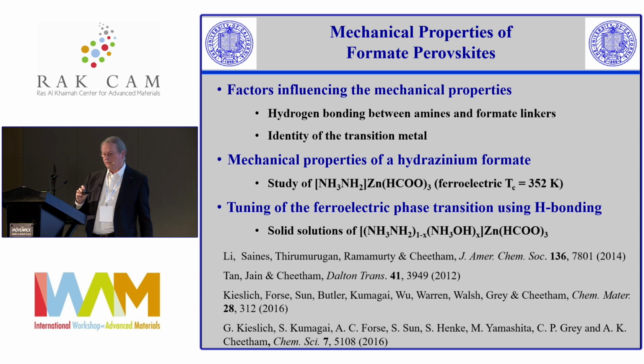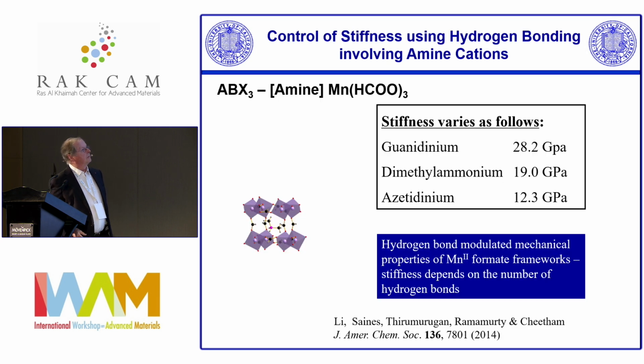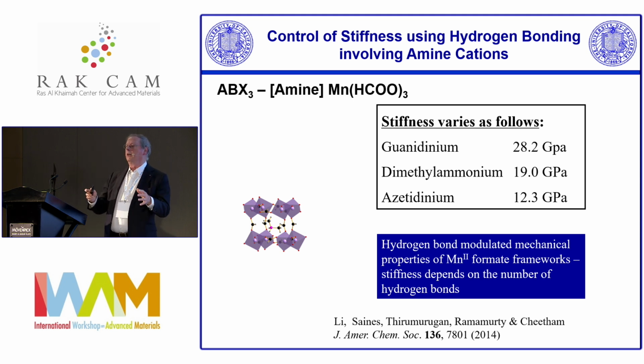So it's a very good high temperature ferroelectric. One thing that we were able to do is show quantitatively that the degree of hydrogen bonding influences the mechanical properties of the system. So this is measuring the stiffness, the Young's modulus, as a function of systems with more and more hydrogen bonding.